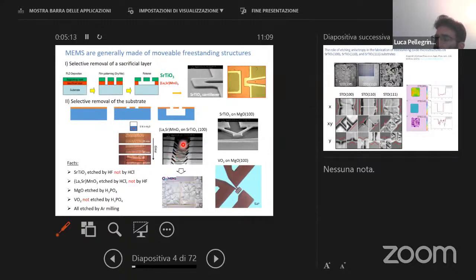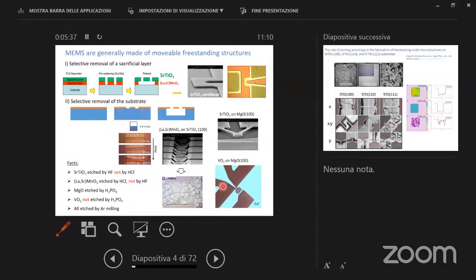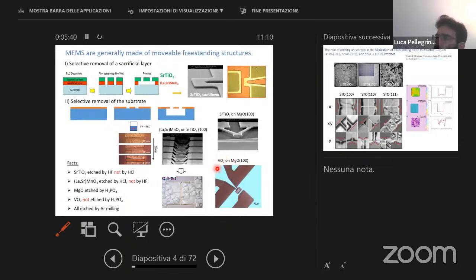And you can see here from this same image what we can do. This is a freestanding manganite bridge, which is 100 nanometer thick, and the width is about 2-3 microns, 5 microns. And I will show you an example later on. We have the same process using vanadium dioxide. This is done in collaboration with Japan. I'll show you later. And this is a freestanding cantilever that is made on MgO 100 substrate, and we use phosphoric acid to remove the MgO that does not etch vanadium dioxide. So we etch all these films instead of using argon milling that we can use to remove the structure easily.